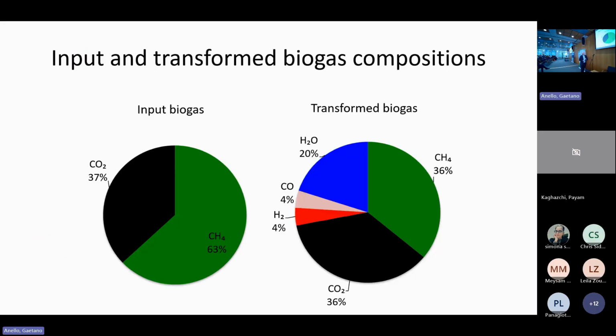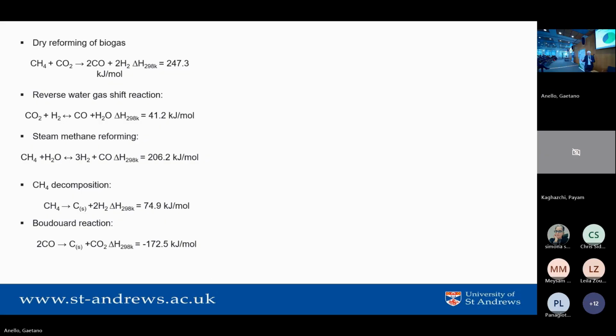And the problem with that is the energy intensity is not sufficient. It's hard to burn it. If you have a bit less CO2, you then have a very attractive fuel, and that's what we're trying to do. When you transform the biogas, you get steam, carbon monoxide, and hydrogen produced when you reform it or do gas shifts on it. There's a whole range of reactions that can occur. Now, as a scientist, you'd like to feed in a gas mix, and you assume that's what's there. But by the time your gas mix reaches your fuel cell or your catalyst at 500, it's not the same as the things you put in.